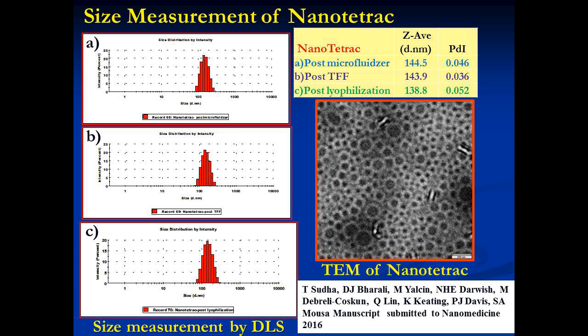To give you an idea about the size of the nanoparticles by dynamic light scattering, it was around 144 nanometers, and it can go down to 120, and in some cases, depending on different parameters, up to 100 nanometers in size, and you can get very monodispersed nanoparticles. The polydispersity factor was 0.046, almost equivalent to a standard you can use in dynamic light scattering. And transmission electron microscopy also supports that the nanoparticles are around 140 nanometers in size.